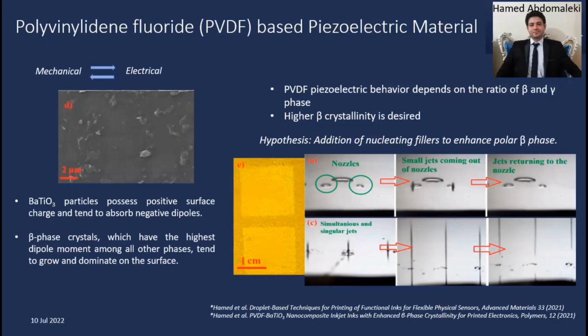So what we did was we set out by using the strategy of using fillers in our PVDF material. And in this case, we chose barium titanate. The idea was to use the positive coefficient of barium titanate and infuse it with PVDF, and then we basically increase the crystallinity of the material. Because in piezoelectric materials, especially the piezoelectric polymers, everything is crystal structure based. You change their crystal structure by a small bit, and their properties will change a lot, right? So their morphology, their size, their crystal dimensions, everything dictates their piezoelectric properties.